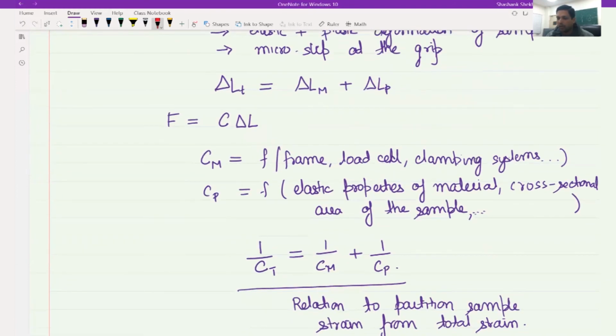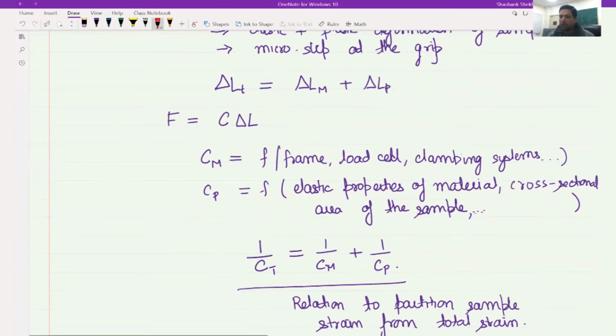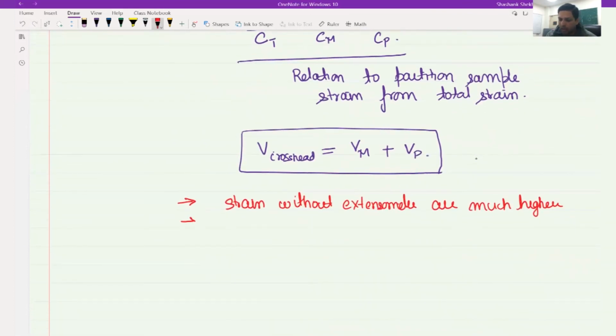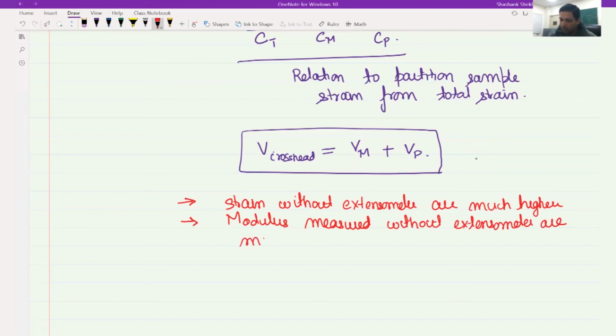Delta LT is equal to delta LM plus delta LP. So this is the delta LT that you're calculating, but this is what you wanted. So this one is much higher than what you wanted. And if the strain is much higher, it means the stress versus strain slope in the elastic regime would be much lower. And therefore, modulus measured without extensometer are much lower.